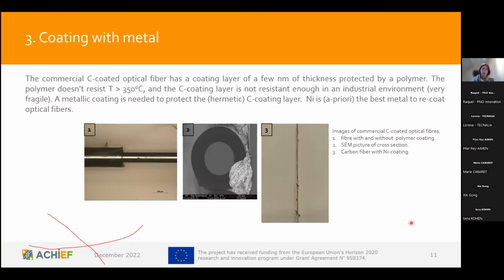The next step now is to coat the carbon-coated fiber with a protective metal layer. This is necessary, as I mentioned before, because the protective polymer coating that is around commercially available fibers as well does not withstand temperatures above 350 degrees C, and we have higher temperature use cases here. So also the carbon coating alone is not robust enough to withstand these industrial environments, so we need the metallic coating. And this has been achieved by AIMEN with an electrodeposition technique. They chose nickel as a first candidate to coat the fiber with, and I learned that that basically is the gold standard of metal you choose if you want to coat something in this type of application.